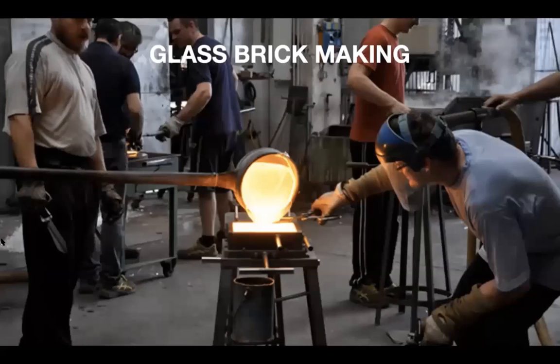If the mold temperature falls below 650 degrees, the hot glass comes in contact with a metal surface and freezes instantly, creating a rippled and wavy surface. If the mold is heated too hot, so above this 750 degrees Celsius temperature, the glass can stick to the walls of the mold and be more difficult to release. A release coating is used on the mold to further prevent sticking of the glass and the formation of micro cracks. So you can see the glass brick makers here pouring that molten glass into the mold there.